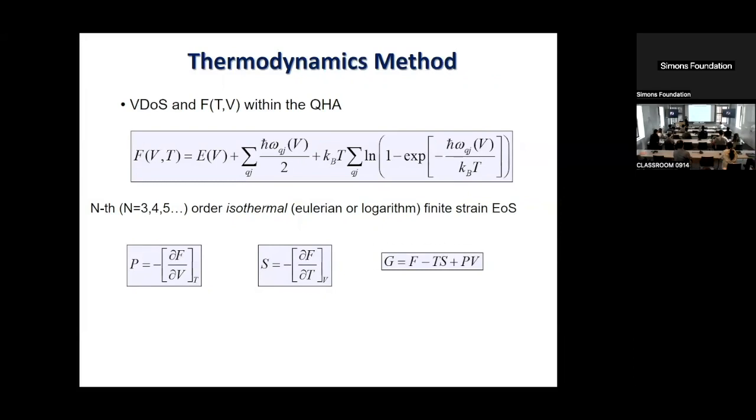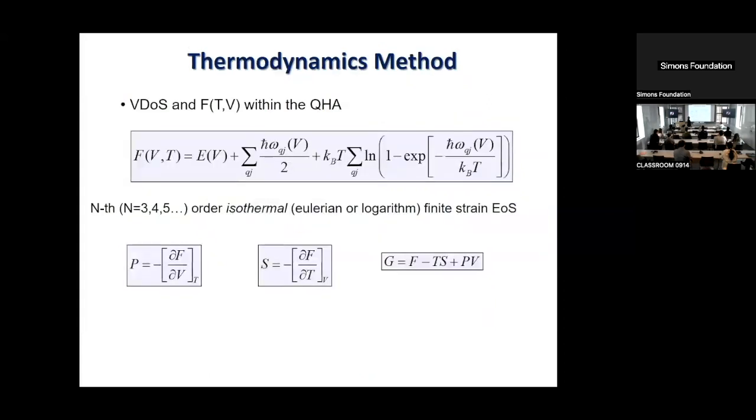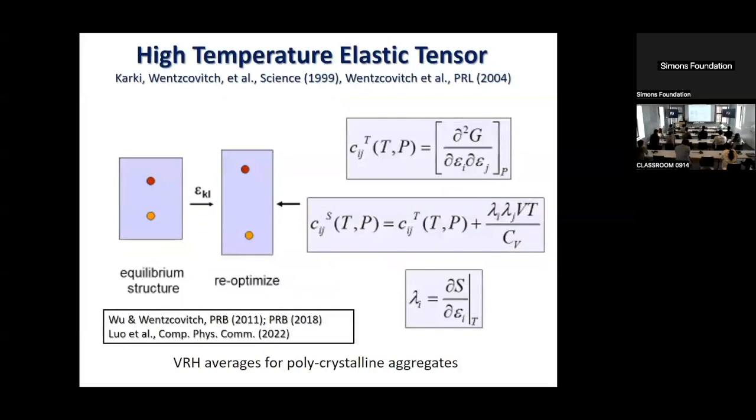And then on the next page, you refer to Gruneisen parameters, which are again that nonlinearity. The point is that you need the strain dependence of frequencies. But your previous slide just said frequencies that depend on volume. Correct. But now you need more information. Exactly. We use some tricks to get the derivative of omega with respect to epsilon from the compression curve, from the compressed structure, because the compression is not isotropic. Tricks, okay? But they work very well.